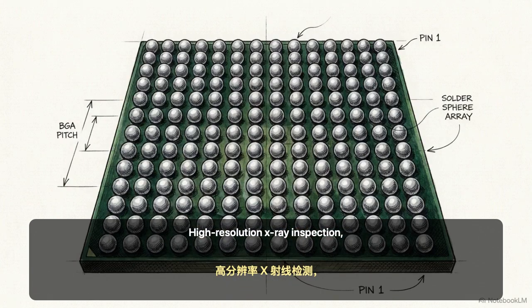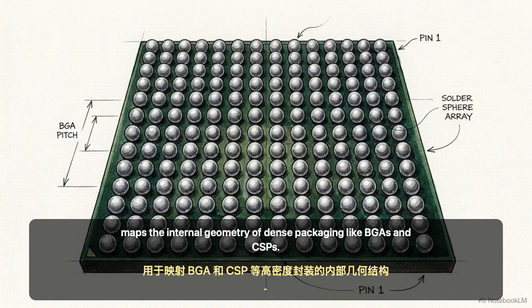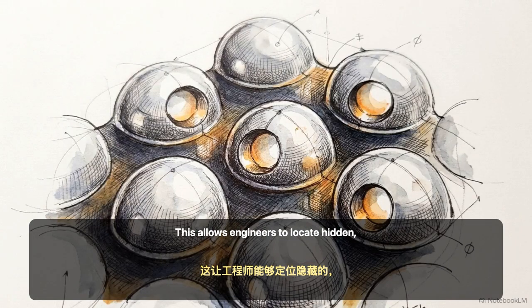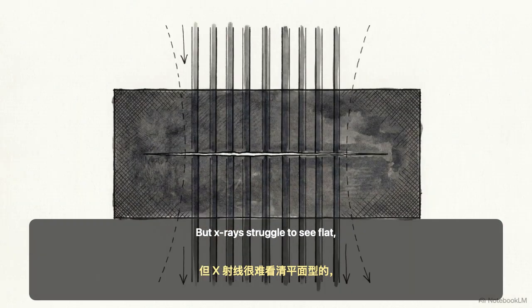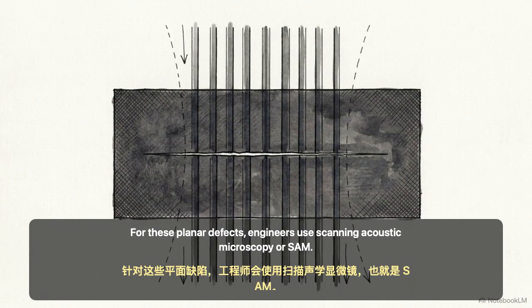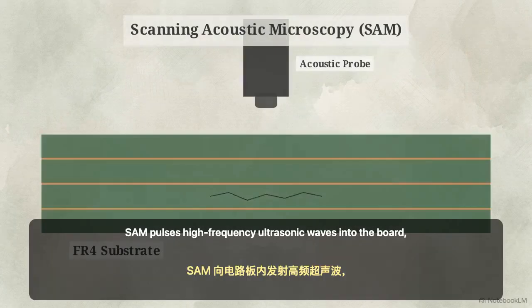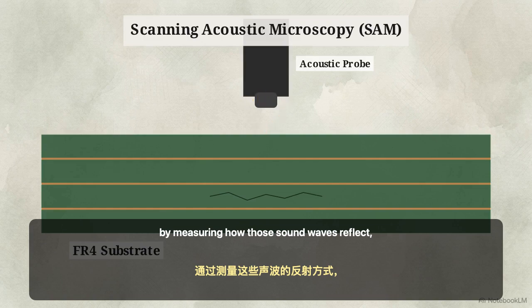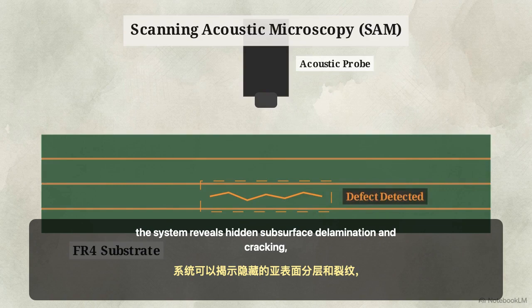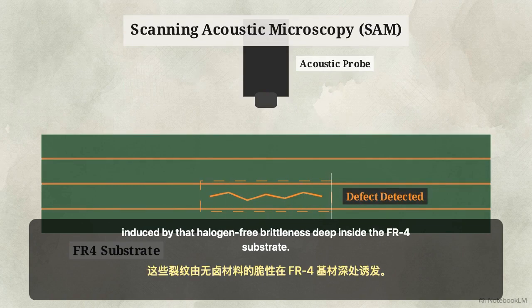High-resolution X-ray inspection, capable of resolving details down to a single micron, maps the internal geometry of dense packaging like BGAs and CSPs. This allows engineers to locate hidden, volumetric voids trapped inside the solder spheres. But X-rays struggle to see flat, two-dimensional separations. For these planar defects, engineers use scanning acoustic microscopy, or SAM. SAM pulses high-frequency ultrasonic waves into the board. By measuring how those sound waves reflect, the system reveals hidden subsurface delamination and cracking induced by that halogen-free brittleness deep inside the FR4 substrate.